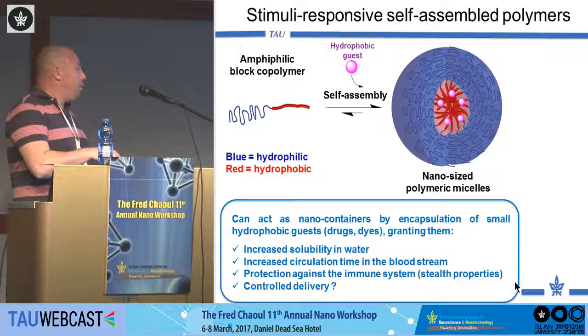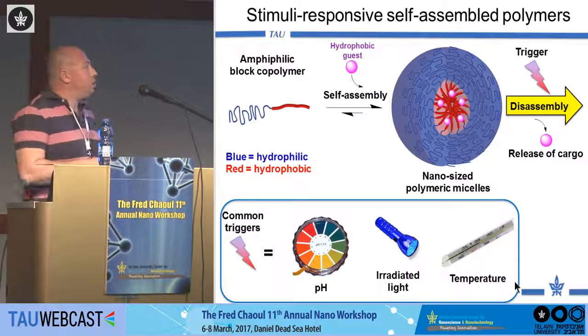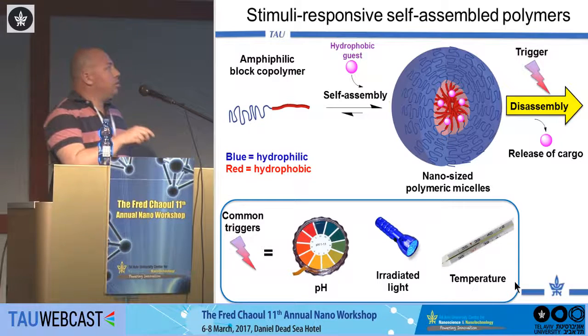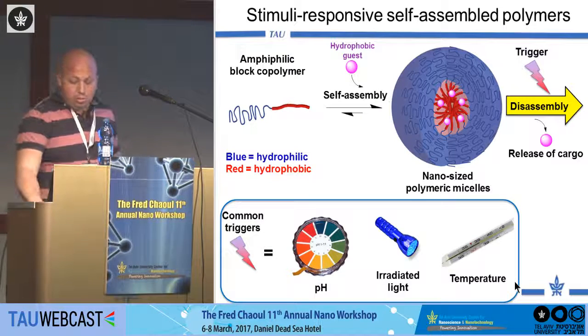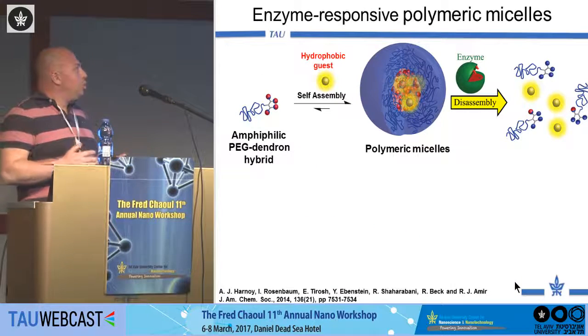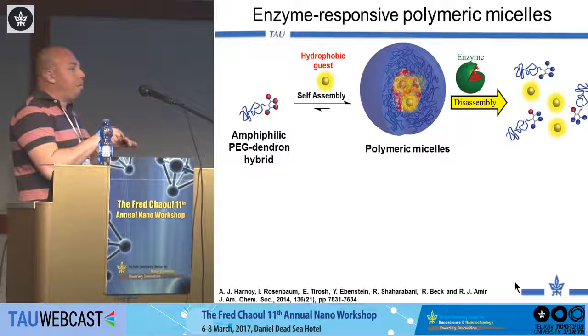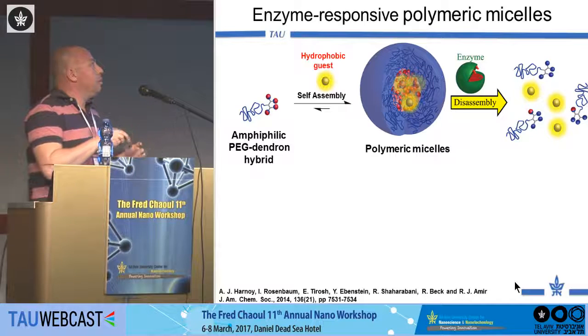So I wrote controlled delivery with a question mark because in the past 15 or 20 years, people have been working very hard to design triggers that can cause the nanocarrier to disassemble and release its cargo. And people have been focusing mostly on pH, light, and temperature as potential triggers. And in our group, we do two things differently. First of all, and not surprisingly, instead of a linear hydrophobic segment, we use a dendron, whose terminal ends are functionalized with hydrophobic end groups. And we design our polymeric micelles to disassemble in response to an enzyme.